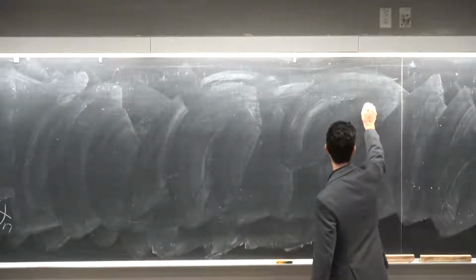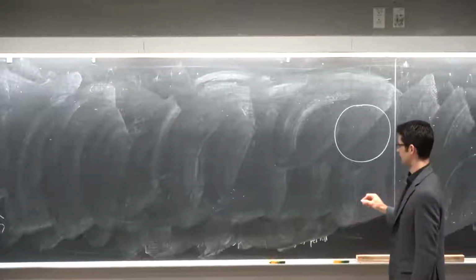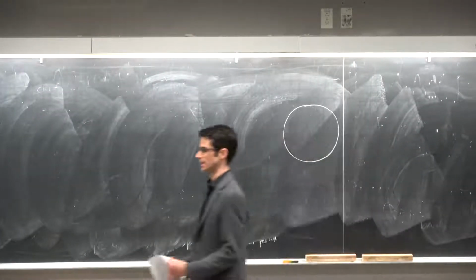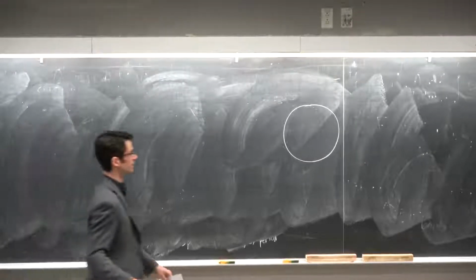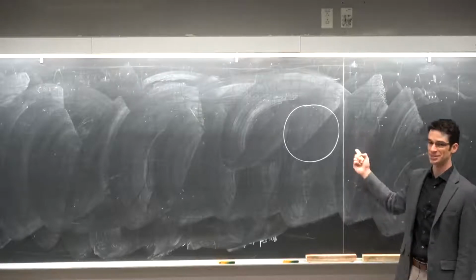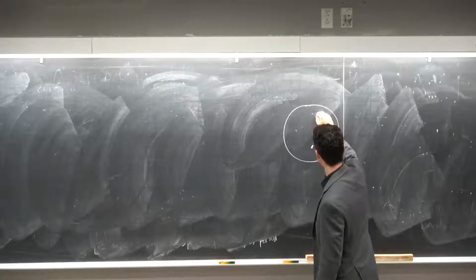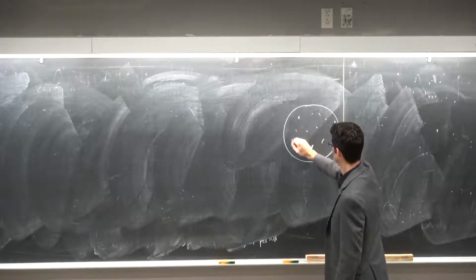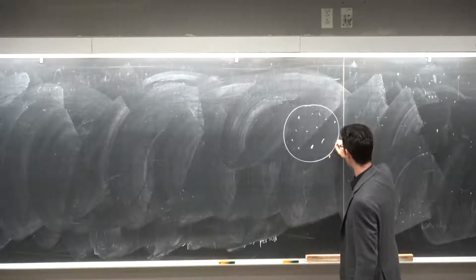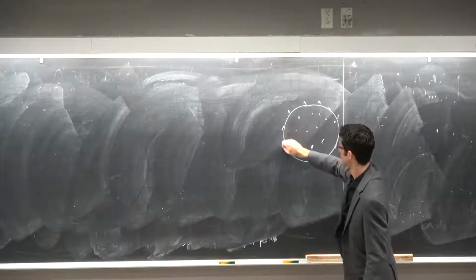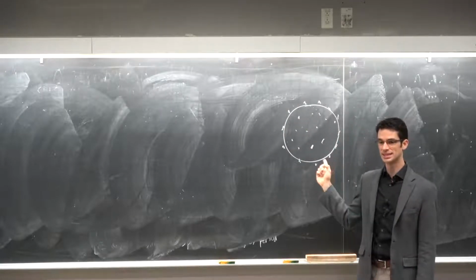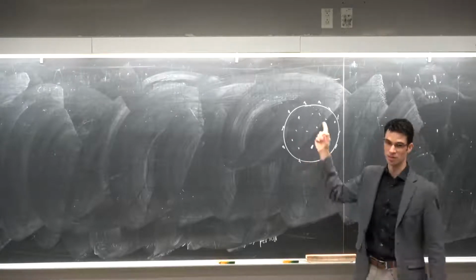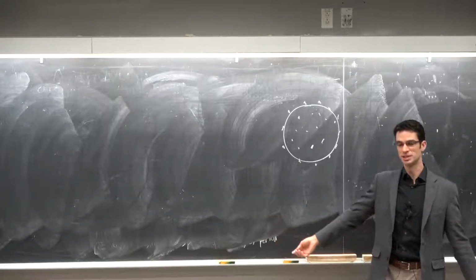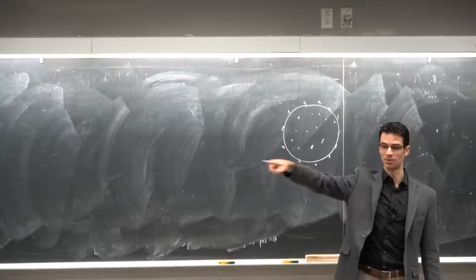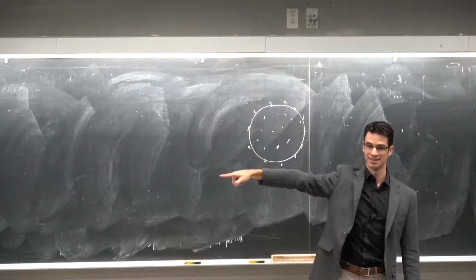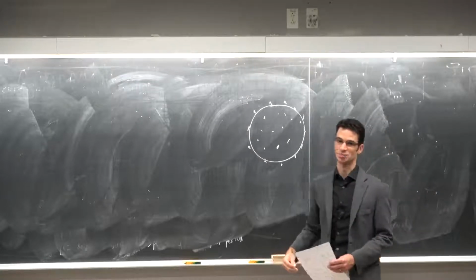So burst release is, say you have some polymer nanoparticle and it's difficult to control during the synthesis whether the drug molecules end up in the interior or on the surface. So say you have a bunch in the interior, but then in the process of synthesizing these nanoparticles, you also end up with a bunch that pepper the exterior. Now, when you release this into the biological environment, all of these are going to come off first, and they come off all at once. So your drug release profile, what you want is perhaps something that's flat, and what you end up with is something that looks like that. Yeah, there's a spike at the beginning.